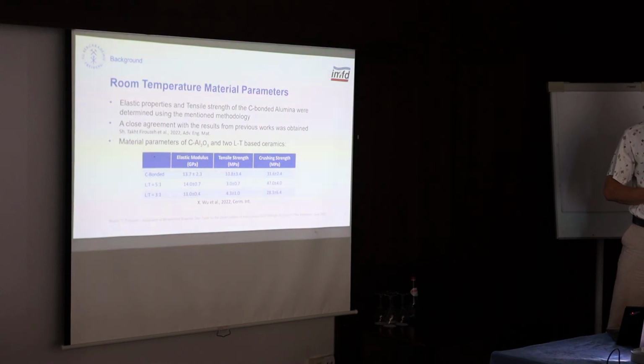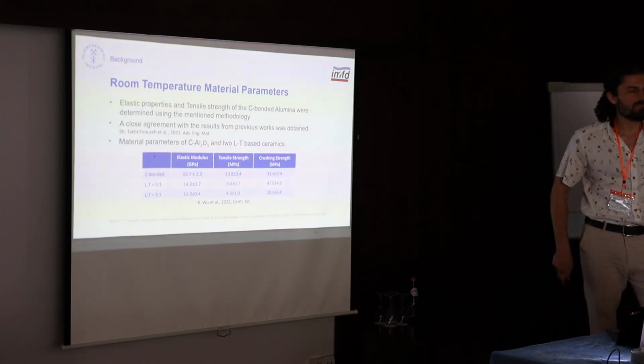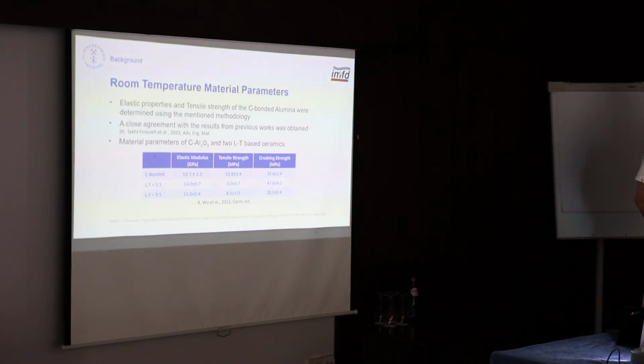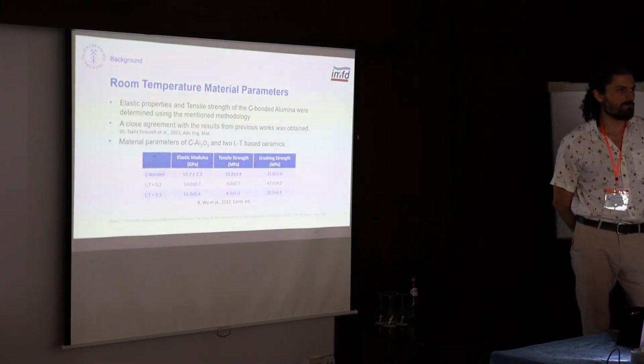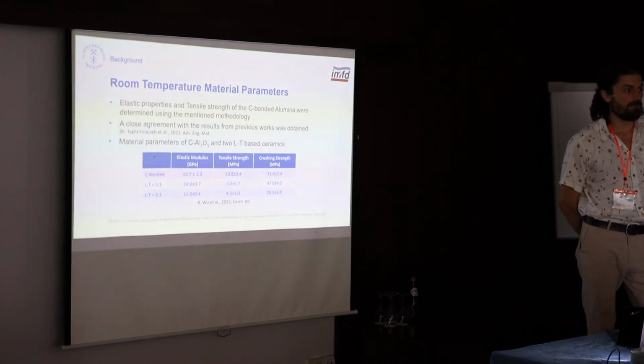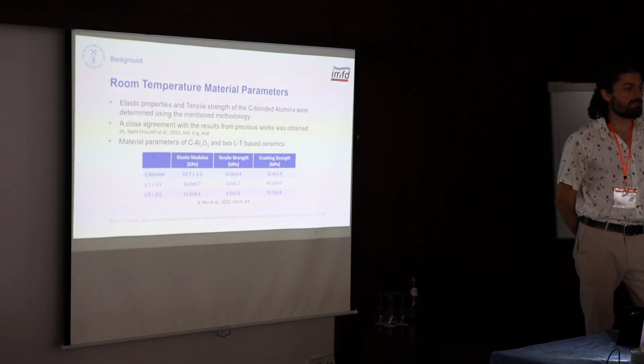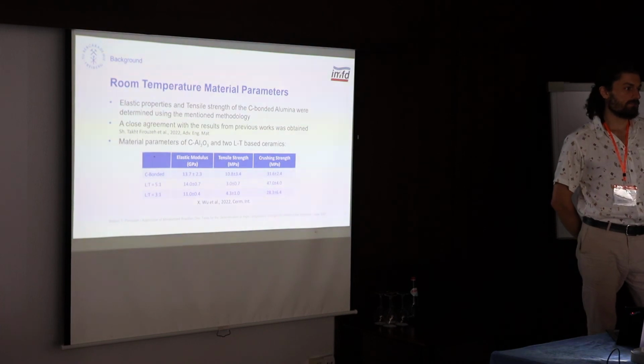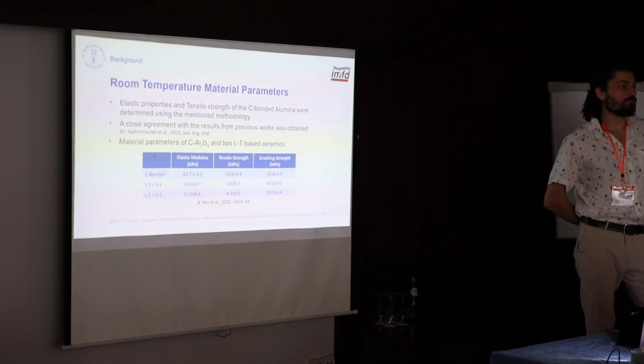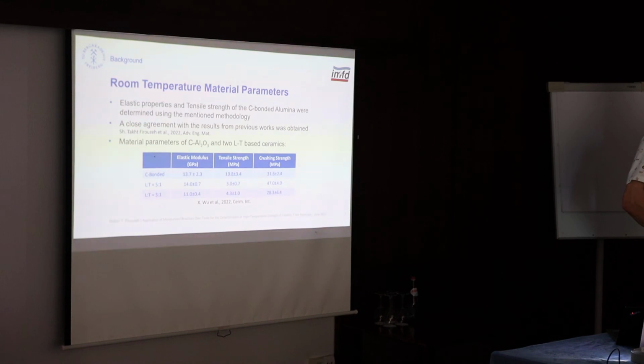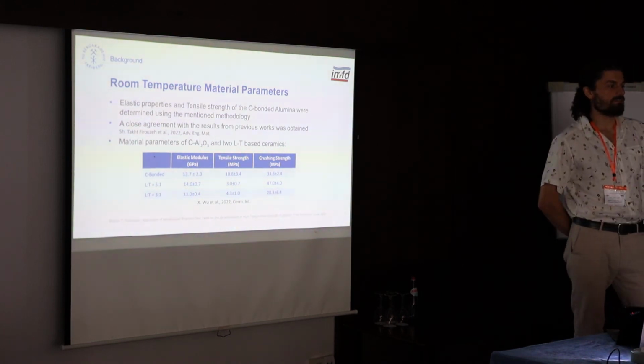Yeah, but you don't know the cohesive energy, right? Yes, for that there have also been other works on the same material using different tests, like the chevron notch test, for example. So starting with these assumptions, I already had a good assumption to start with, which is also obtained from the same material. But also, when I just took the displacement of the cohesive elements as my damage criterion, I also didn't get too far from my results.